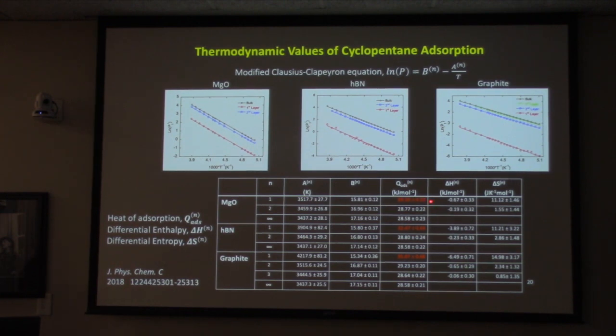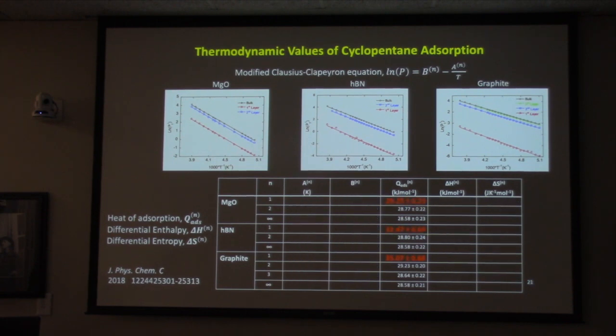One of the things that's interesting is you can actually see in this case that the binding energy of cyclopentane to graphite is the highest as compared to boron nitride and magnesium oxide. And at some level, it's interesting because it's pseudo five-fold symmetric. It shouldn't like any of those systems. But when it's close to the 6-fold ones, it really likes to sit there. So I've enlarged it here so you can see those. It allowed me to tell you the wisecrack.